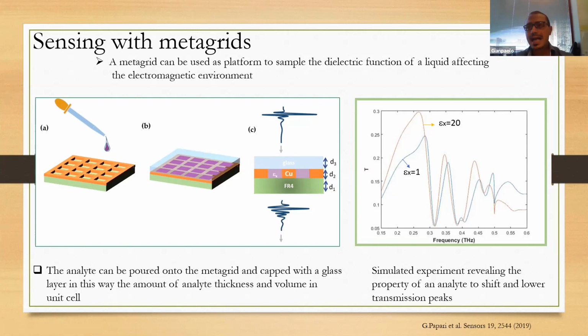So just having in our database the way these peaks shift according to epsilon x, we can provide a sampled dielectric function, because we studied just the peaks, so just a few points to characterize the dielectric constant, over a band of about 1 terahertz, half terahertz in this case. And so sampling, we have a fast way to characterize an unknown analyte, just creating a database on the shift of these peaks.